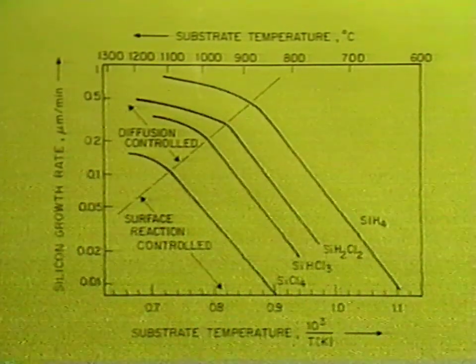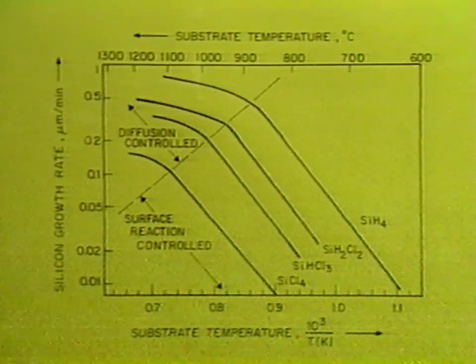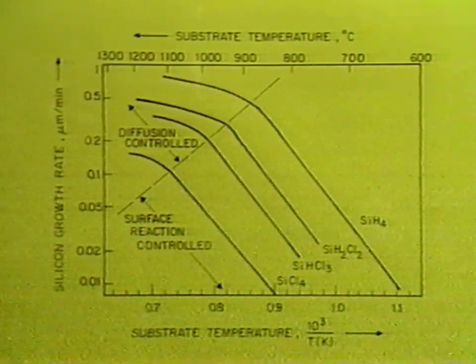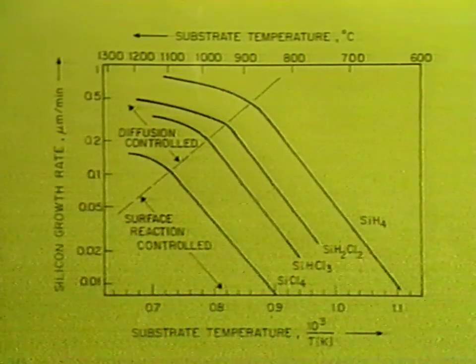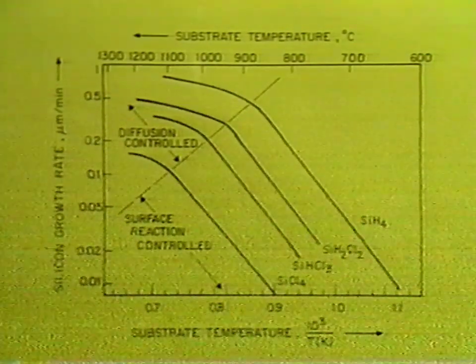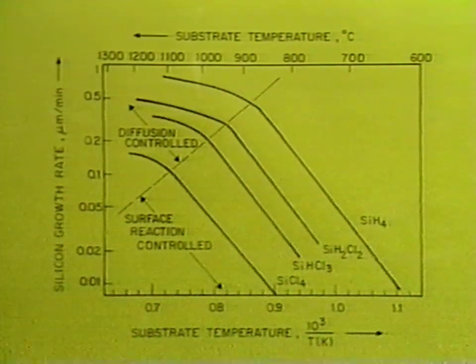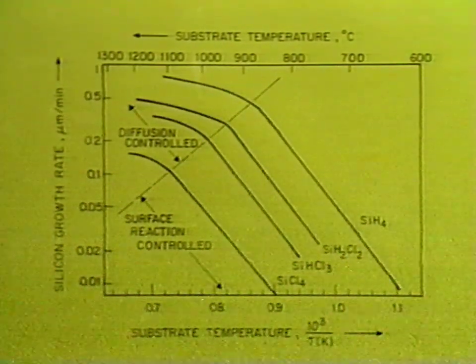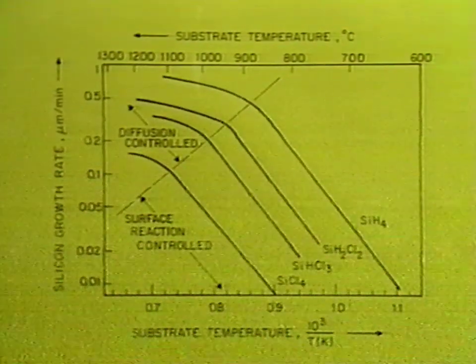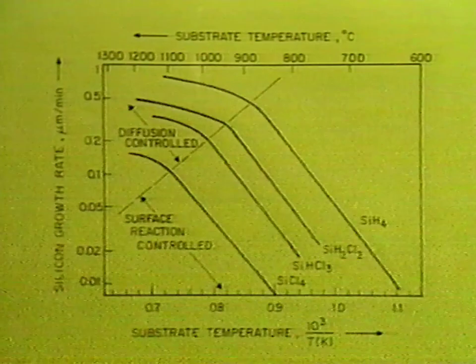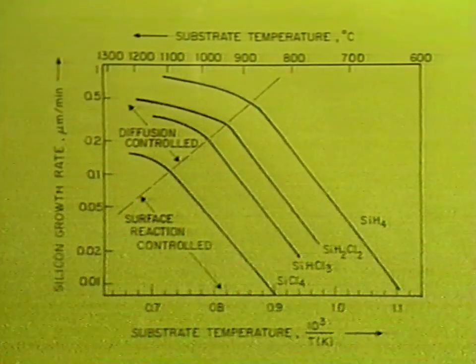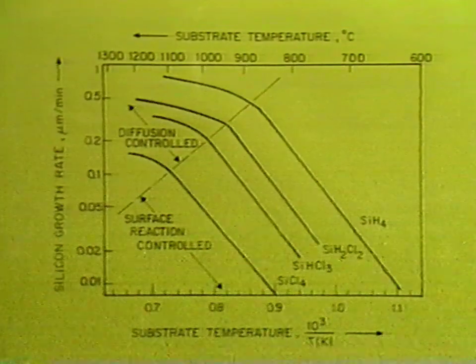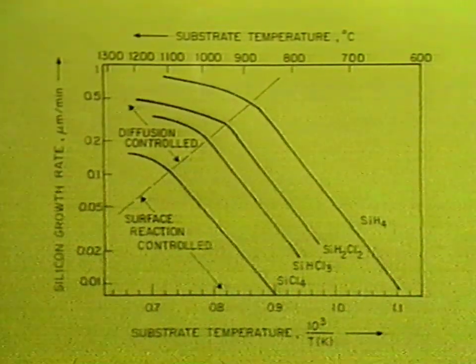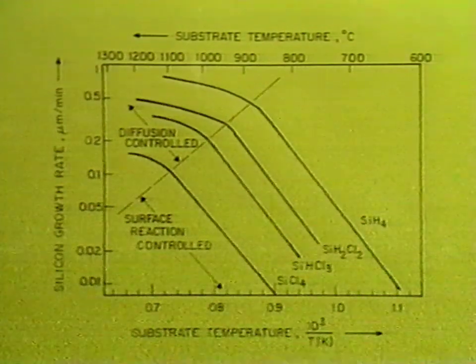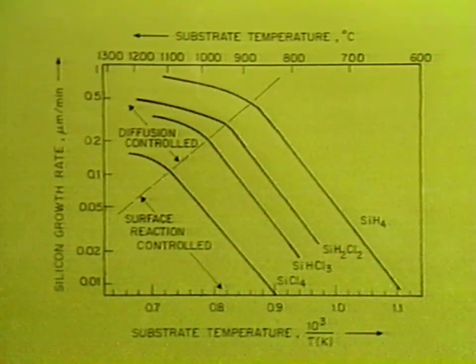However, we definitely see 2 types of curves, a very steep one going from the right to the left, and in this case, that's the lower temperature type process, which has an exponential temperature dependence, very steep, very sensitive to temperature, then reaches a knee on the upper part of the curves and levels off. So all of the curves then level off at a higher temperature end, which are the diffusion type processes, which are not influenced to any great degree by temperature. So that is a very general type of behavior that holds for most of the types of processes.